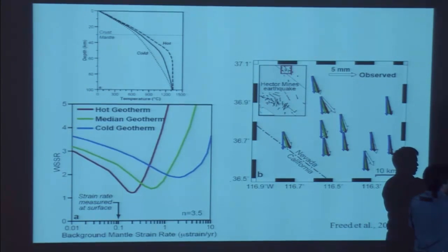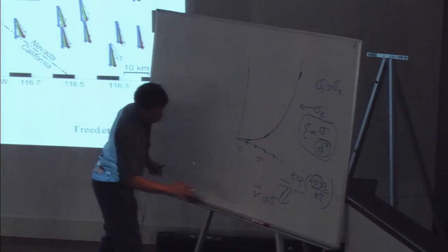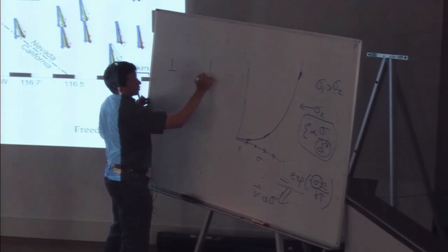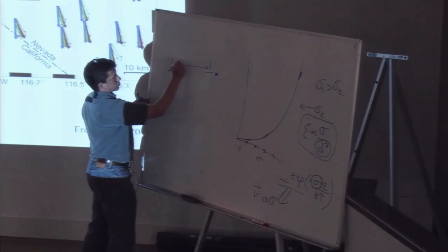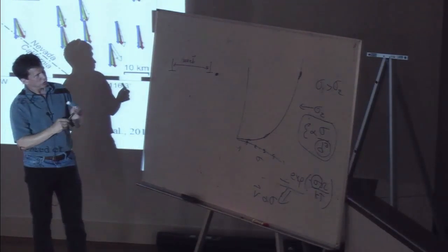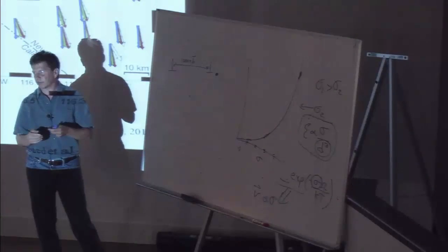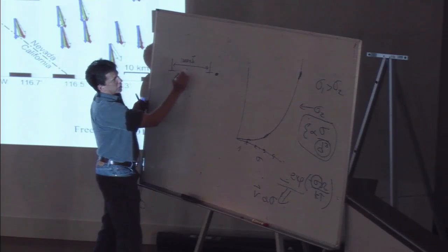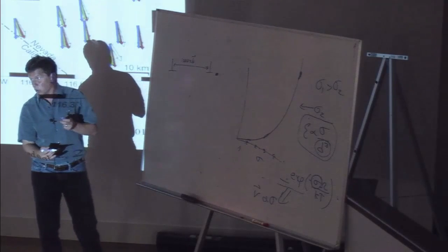He's asking about, are there conditions where the dislocation glide is more important than dislocation climb? And so I'm going to draw my upside-down T cartoon here. So if you look at dislocations in crystals, the spacing of the dislocations might be in the range of 1,000 unit cells, something like that. So the idea is that this process, the glide process, is very simple.